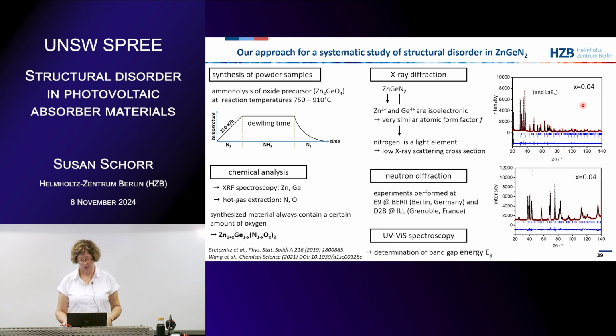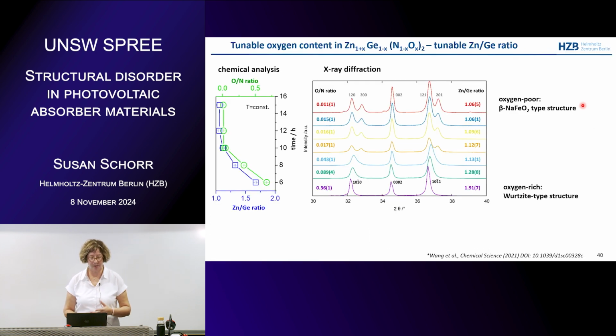And again, we do UV spectroscopy to get the bandgap energy. But this is just an overview of a part of the X-ray diffraction pattern of some of the zinc germanium nitride samples, where we have a changing zinc to germanium ratio, which we get from the XRF measurement. And with this, the oxygen to nitrogen ratio changes, because when we have more oxygen in here, we come to these zinc germanium ratios. So they correlate with each other. You see here, for one of the temperatures, for different reaction times, we can change the oxygen to nitrogen ratio, and with this changes the zinc to germanium ratio.